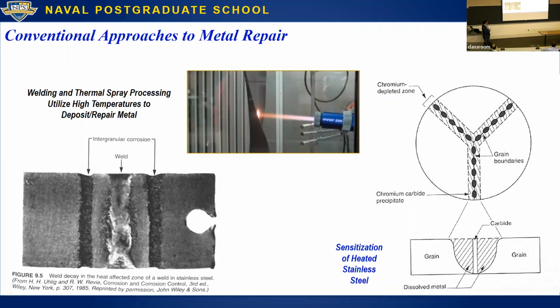To back up a little bit, why cold spray? Other techniques that are used for repair are inherently high temperature. The competitors are mostly thermal spray, which is an analogous idea, except you're not using a cold gas, you're using a combusted gas or even a plasma flame, which is going to melt your particles. And those systems are designed to melt it. So this is an HVOF system. You're shooting particles into this combustion flame. And yeah, you can use it to coat very large pieces. So it's very scalable.